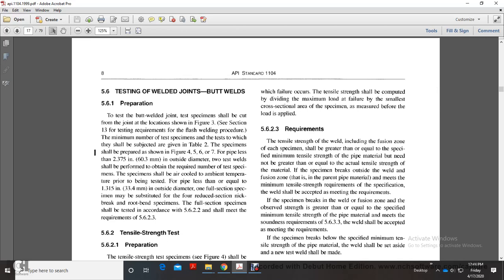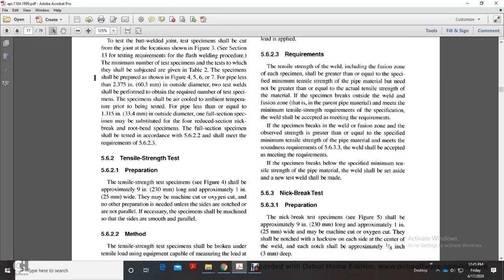For pipes less than 2.375 inches outside diameter, two test welds shall be performed to obtain the required number of test specimens. Specimens shall be air-cooled to ambient temperature prior to being tested. For pipe less than or equal to 1.315 inches outside diameter, one full section specimen may be substituted with a reduced section nick break or root bend specimen. Full section specimens shall be tested in accordance with 5.6.2.2 and shall meet the requirements of 5.6.2.3.